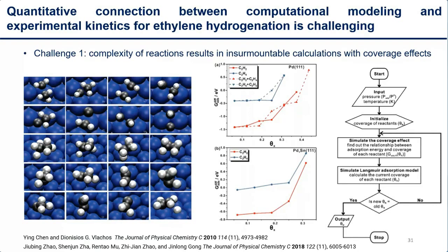And this chemical complexity has really been captured already in the open literature by those performing density functional theory calculations coupled with microkinetic modeling. One of the primary challenges associated with modeling ethylene hydrogenation is that there are just a vast number of possible coverage conditions that are encountered as we change temperatures and ratios of partial pressures of ethylene and hydrogen.